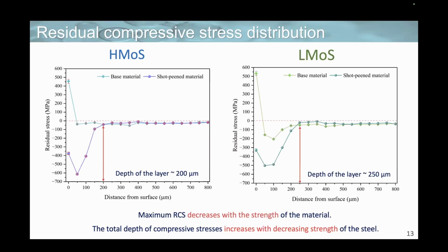The question was what is happening with the residual compressive stresses in our materials. And for this purpose, we did residual compressive stress profiles. And we can see from these results that the highest value of residual compressive stresses was reached for the high molybdenum steel, and the depth of layer was 200 micrometers, while the lower value was reached in the case of low molybdenum steel, and the depth was 250 micrometers. So we can say that maximum residual compressive stresses decrease with the strength of the material, while the total depth of compressive stresses increases with decreasing strength.